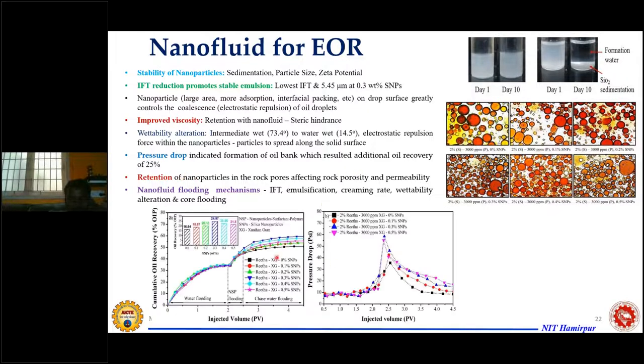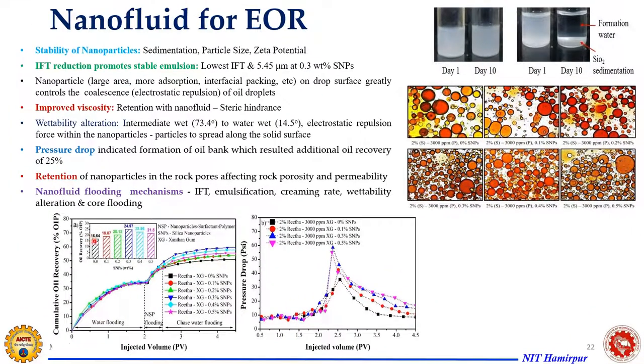And then when we do this flooding, you can see here more or less the same pattern. When you have no nanoparticles, the recovery was a little bit high, around 70%, because you have surfactant as compared to the previous case. And then you can see here we are getting around 25% of oil recovery, which is also pretty much higher as compared to the case where we have used only polymer flooding. Here we have used polymer, surfactant and nanoparticles.